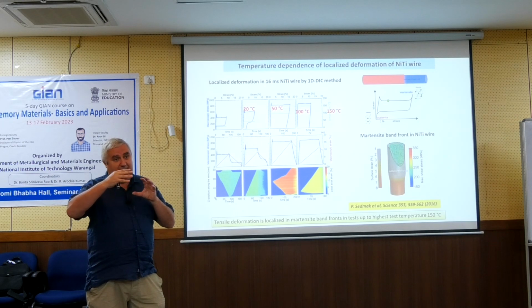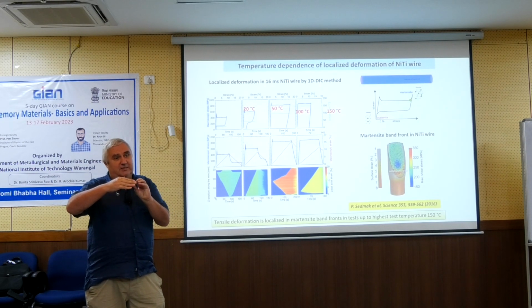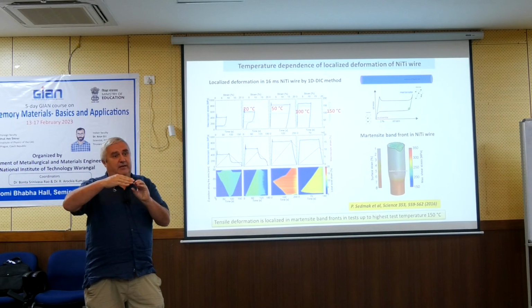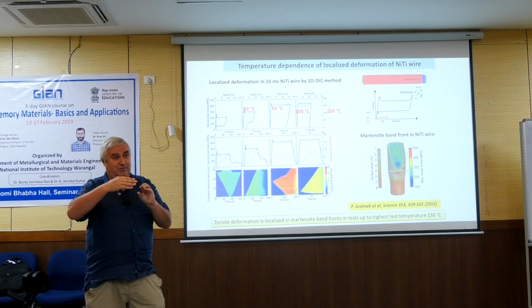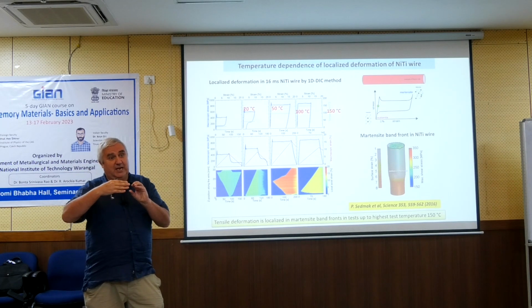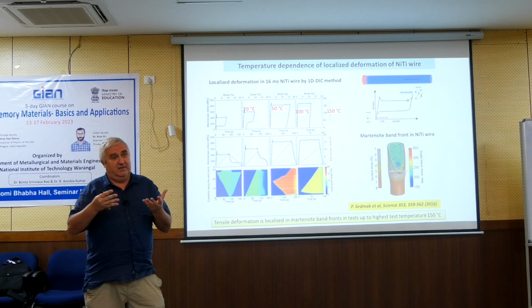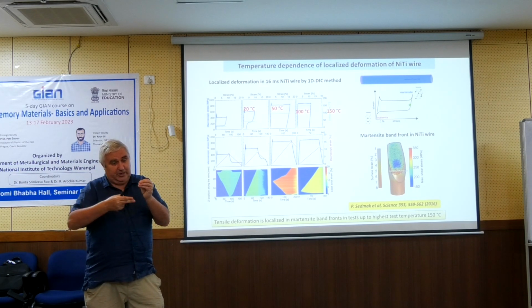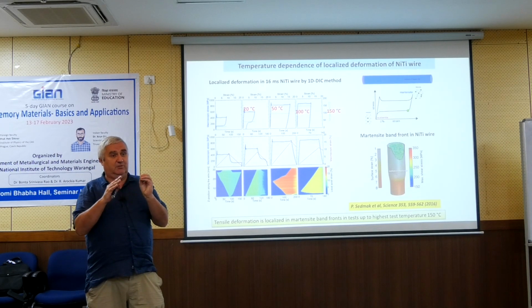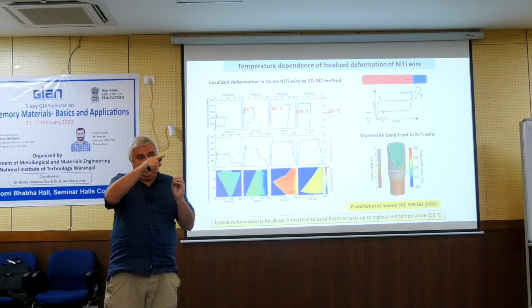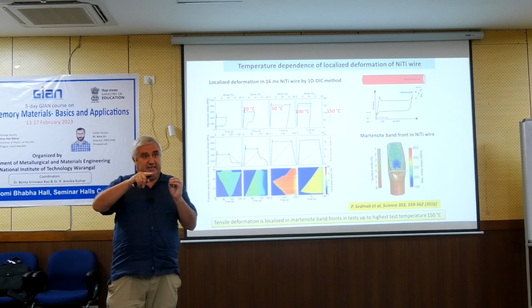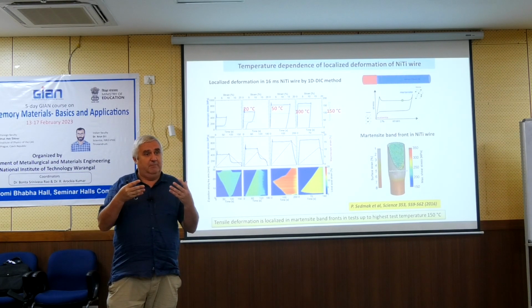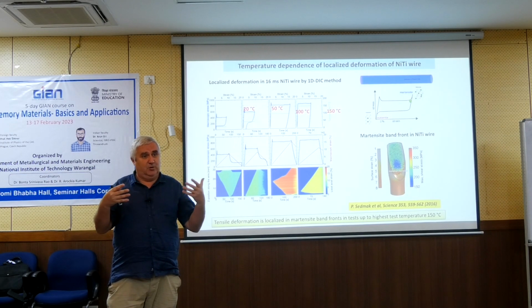maybe by loading you supply energy, and some part of this energy is dissipated into heat, latent heat. But latent heat is compensated on cooling, but also is dissipated into the defects which are created. You hear a sound, so there are elastic waves, and all this energy is lost. And if you have some lost energy, you have hysteresis. This occurs during forward and reverse transformation. During both transformations, some part of the energy is lost, and if you take the area of this hysteresis, you can convert it to the dissipated energy by thermodynamics approaches, and you can calculate that.